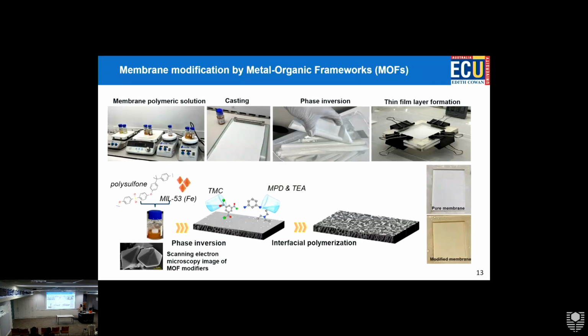So here I brought some examples of how membranes are made to make it more sensible basically. With membranes, the R&D projects start with flat sheet membranes normally. So we develop flat sheet membranes, test them if they are efficient. They go to the commercial membrane fabrication sites, and then they get rolled into lots of sheets and then fit into modules. Or the same synthesis process is going to happen for the hollow fiber membranes. So they do spin coating and other stuff with the same procedure and create membranes in a module that look like spaghetti rolls, something like that. If you visit wastewater treatment plants, they normally have samples of those membranes present there, but all of those membranes have started from a flat sheet, basically.